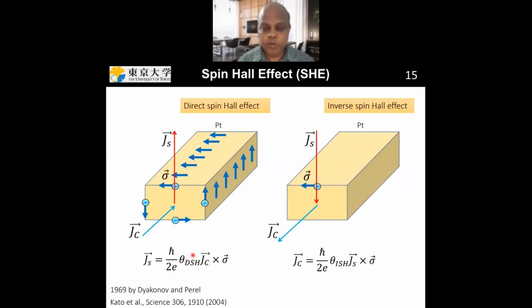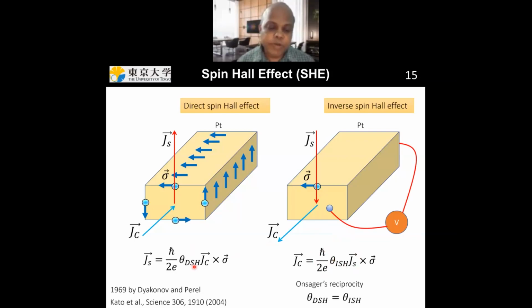And the reverse process is also true. You can inject spin current into a piece of platinum, and you can create a charge current, which will be mutually orthogonal to the spin current direction and spin polarization direction, whose magnitude will be given by this expression over here. Here you can see that there are two spin Hall angles. One you can determine from the direct spin Hall effect, and the other you can determine from the inverse spin Hall effect. Usually, due to the Onsager reciprocity, they have equal magnitude.